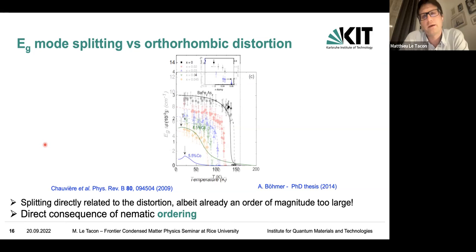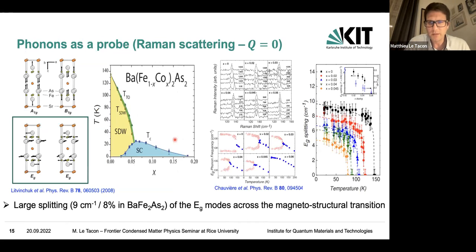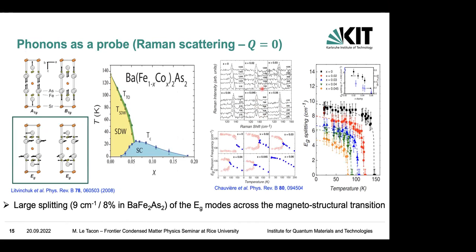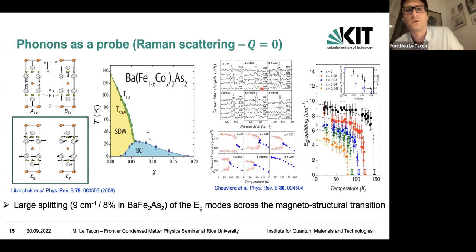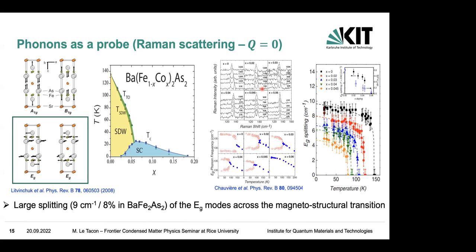I don't know. I'm not sure whether this was looked at carefully, simply because I think it was mostly a curiosity, and I'm not sure they paid attention to that. If you look here, this was done carefully at the 4.5% level, and they didn't really go down to very low temperatures. Also, back then the quality of the data which I show, the EG phonons are something which is not so easy to measure, because you need to take your sample and measure it from the side with the polarization along the z-axis and things like that.